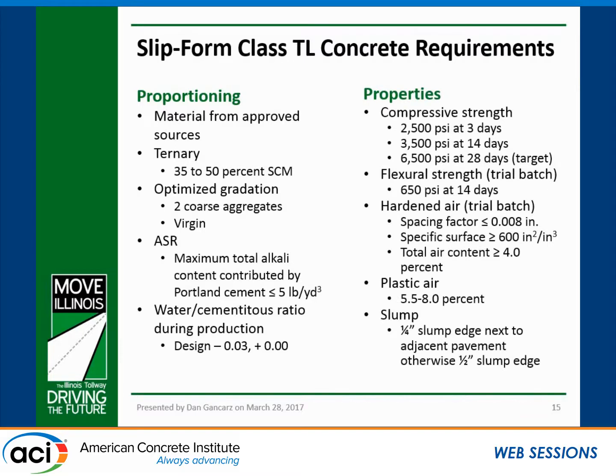So for our pavement mixes, what we're looking at is compressive strength. So we have a 3-day strength to get construction traffic on it at 2,500. Our design strength of 3,500 PSI at 14 days. And then we also have a 28-day target strength of 6,500 PSI. And this 6,500 PSI is used for the performance-related construction spec, and we selected it to be a little higher to accommodate the SEM usage. So we know it's high for a pavement application, but it's meant to accommodate the SEM usage.